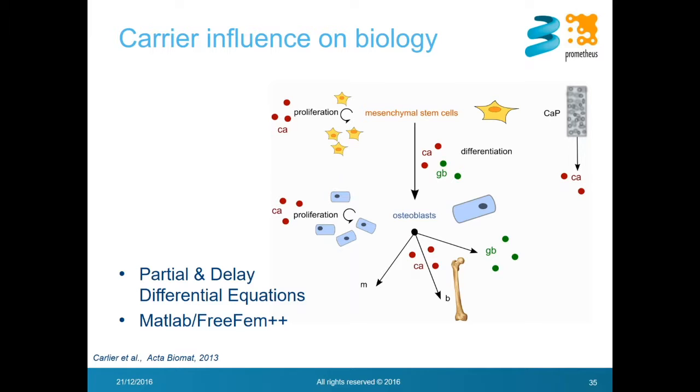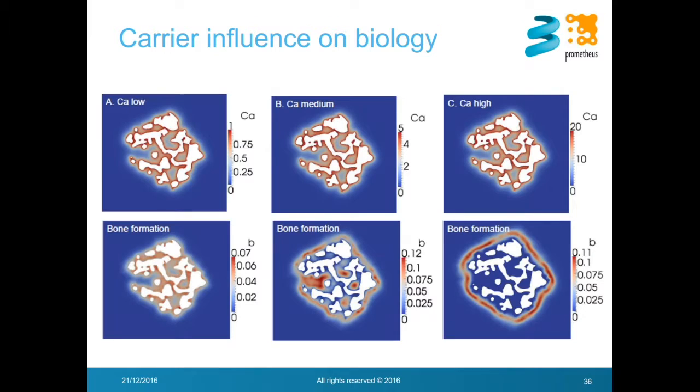This is a partial differential equation model that we implemented in MATLAB or in FreeFem. And what you see here, because the study is still ongoing, are 3 different case studies to show proof of concept, where you have a different amount of calcium dissolution from the scaffold: low, medium, and high. And you see that the bone formation response is vastly different depending on the release rate of these calcium ions.